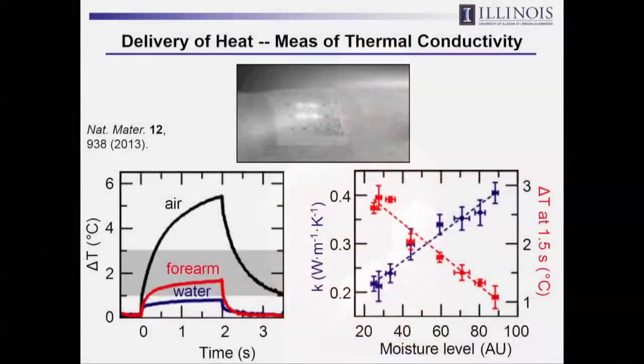But what's additionally interesting about these platforms is you can do temperature sensing, but you can also do precision delivery of thermal power to the skin. So you can heat the skin by very minute amounts, and then you can measure simultaneously how that heat moves laterally through the skin and down into its depth. And so here's an IR camera showing one of these devices with 4 pixels lit up, and these sensors can then be used to track thermal diffusion. And it turns out then you can determine the thermal conductivity, the thermal diffusivity, and the heat capacity of the skin with these same platforms.